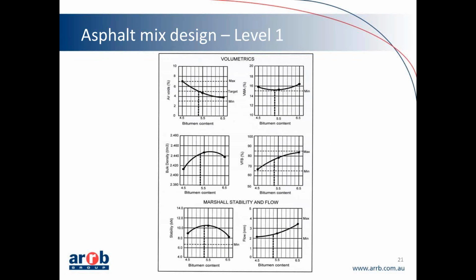If we are conducting a very detailed design, we prepare specimens with a target binder content plus minus 2 other binder contents, which is a 5-point Marshall design. A simplified process, which you can see on this slide, refers to a 3-point design where we are targeting a binder content plus minus 1% below and above this target. Of course, once we have plotted these values against the binder content, we do an analysis and compare the results with the relevant specification requirements.